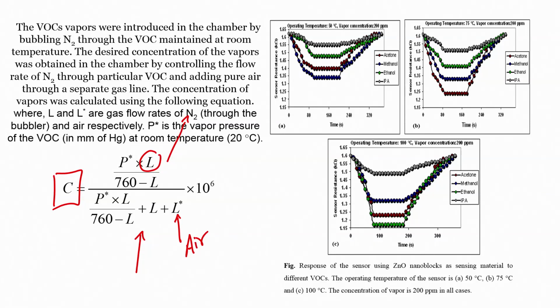Now, you see here, the response of the sensor at different temperatures we are measuring. At 50 degree centigrade, you can see that the response to methanol is higher compared to acetone, ethanol and IPA, while at 75 degree centigrade the sensor shows more sensitivity to acetone, and at 100 degree centigrade the sensor is showing a higher sensitivity for ethanol.